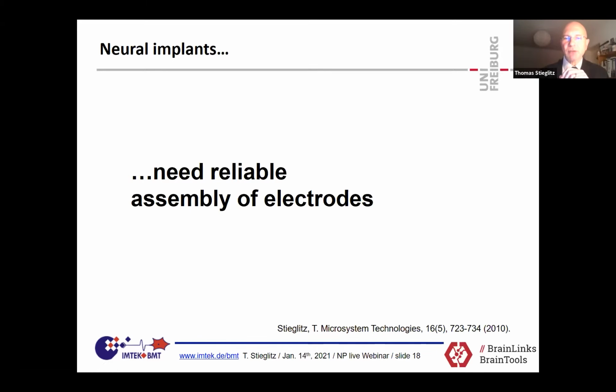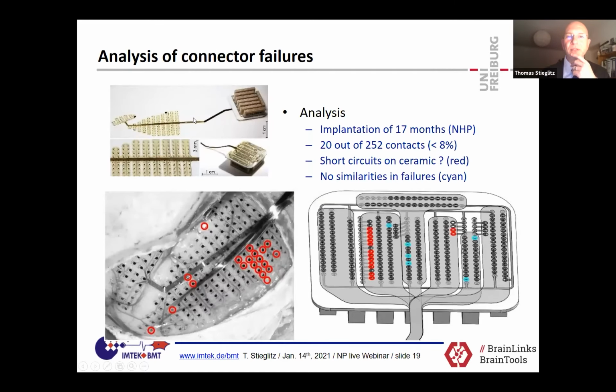If you would ask somebody from outside the field, say, hey, what do you think a problem is? Nobody would come to the idea that the assembly of the electrode is one of the really hard things. And the more electrodes you get, the harder it gets. And the reason for that is that you need a lot of interconnect cables. One electrode, one cable goes to one pin of one connector. And this array here of 252 contacts has seen a non-human primate for about 17 months, and it worked well. And at the end of those 17 months, less than 8% of the channels dropped out, 20 out of 252, and they were not really gone, but their signal looked like the signal on the neighboring pin.